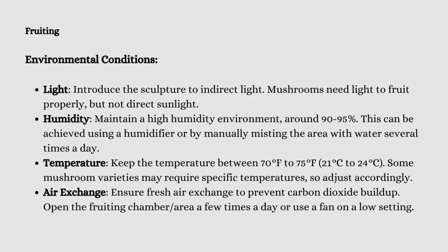And then temperature: you want to keep the temperature at 21 to 24 degrees, which is different from what we spoke about earlier. 21 degrees is great. This is the sweet spot for a lot of different strains, especially ones that we're going to be using for myco-materials. However, this can change depending on what strain you're using, so it's always good to double check online. There are a ton of resources and repositories where you can check what your mushroom fruiting conditions should be and adjust accordingly.